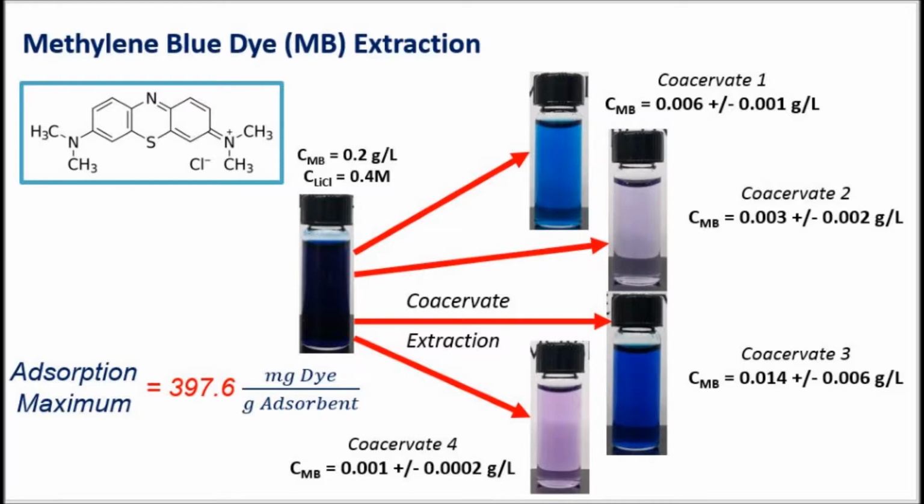Maximum dye adsorption for our coacervate adsorbents approach 400 milligrams of dye per gram of adsorbent, which is 4 times as efficient when compared to conventional methods such as activated carbon.